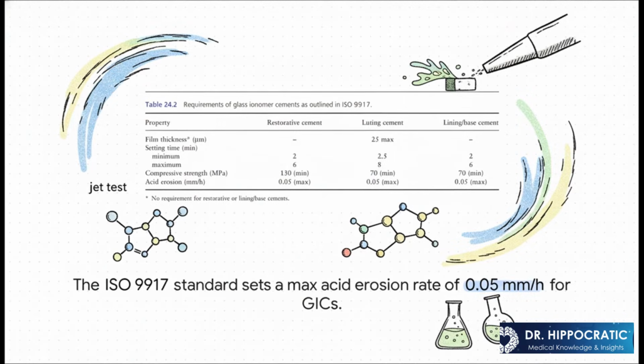And here it is, the official requirement straight from the ISO 9917 standard. You can see it right there. For every type of GIC, whether it's for a filling, cementing a crown, or just acting as a protective base, the maximum erosion is that 0.05 millimeters per hour. And they measure this with something called a jet test, where they literally blast the cement with lactic acid to see how much of it disappears.